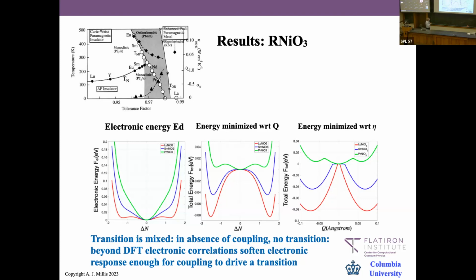So what you see is that the purely electronic energy, actually only for the most strongly correlated one, does it even have a metastable minimum? For all the others, the electronic energy is just purely concave, all right? And then this is what I showed you before. You'll notice that the green one, praseodymium, which is experimentally ordered, in our calculation — and we didn't adjust anything — is not quite ordered. This thing is a little higher than that. So that's the level of errors and uncertainties in the calculation.